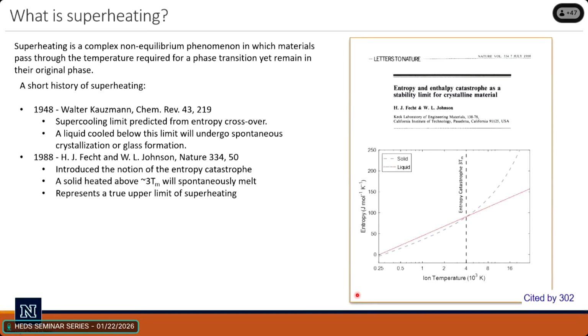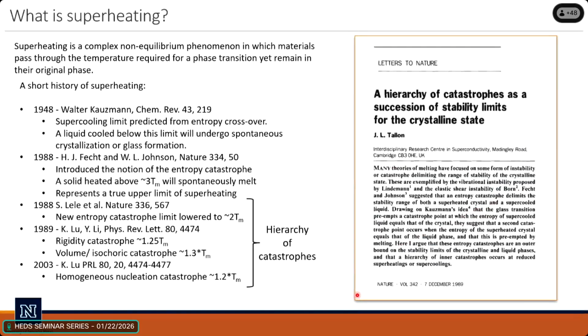And it's harder to try, so only 300 citations, 1/10 of the number of citations, because it's much harder to rapidly heat something up and see how hot you can make it than it is to cool it down. In addition, there are lots of other things that cause essentially melting to happen before you can even try to get to the ultimate limit at 3. There's lots of other limits at like 1.25 and 1.3 times the melt temperature. And I'll say one of the reasons I think this work got so widely recognized is because each of the ways in which they can melt are called a different catastrophe. So you have the entropy catastrophe, the rigidity catastrophe, the homogeneous nucleation catastrophe, and together they're called the hierarchy of catastrophes. And that's a sexy name for anything in science, right?